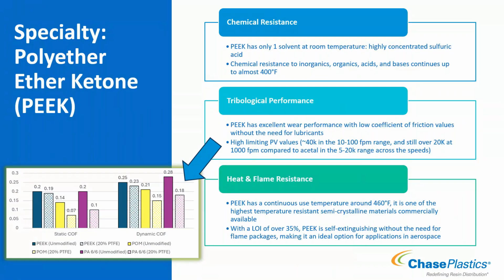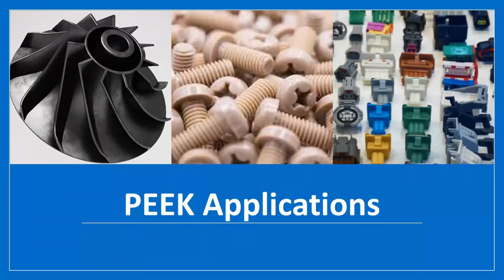Heat performance: continuous use around 460 degrees F. It's one of the highest commercially available semicrystalline grades for thermal performance. It's also self-extinguishing like LCP, with an LOI of over 35%, meaning it needs more than 35% oxygen to continue to burn. So great self-extinguishing performance without flame packages needed, and good temperature performance. This makes it good for applications in aerospace, so it is used in aerospace applications. Some main applications might be propellers, maybe plastic screws utilized for light weighting in aerospace, different connectors. I understand those pictures of connectors aren't necessarily PEEK, but to give an idea that they are used in connectors—PEEK is used for high temperature connector applications as well.